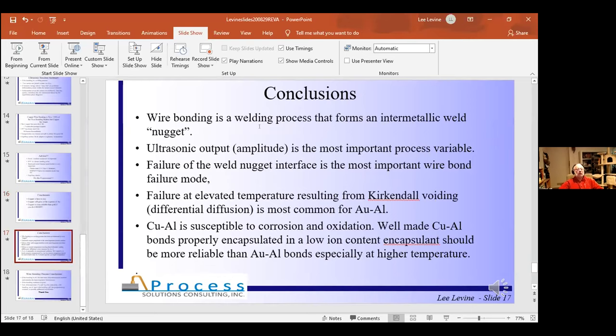Sounds good. Wire bonding is a welding process. It forms an intermetallic weld nugget. Ultrasonic output, the amplitude, is the most important process variable. Failure of the weld nugget interface is the most important wire bond failure mode. Failure at elevated temperature resulting from Kirkendall voids, and that is a differential diffusion, is most common for gold aluminum. Copper aluminum is susceptible to corrosion and oxidation. Well-made copper aluminum bonds, properly encapsulated with a low ion content encapsulant, should be more reliable than gold aluminum bonds, especially at high temperature.